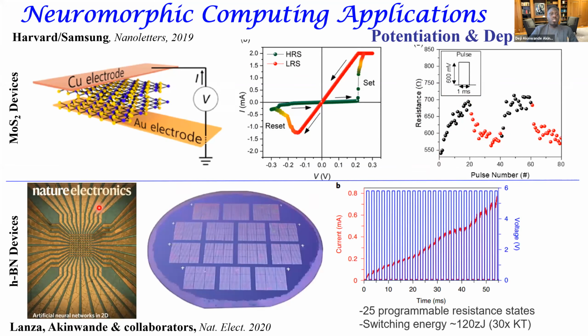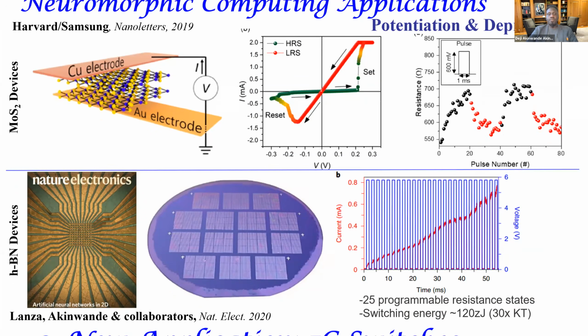Recent collaboration between Mario Lanza, myself, and others showed wafer scale, using HBN in this particular case, wafer scale neuromorphic computing, and we could show 25 programmable resistance states. The point I want to emphasize is in these devices, we could get switching energies of around 120 zeptojoules. This is the lowest switching energy reported so far - we're just 30 times above kT. So very, very interesting for energy efficient computing platforms.